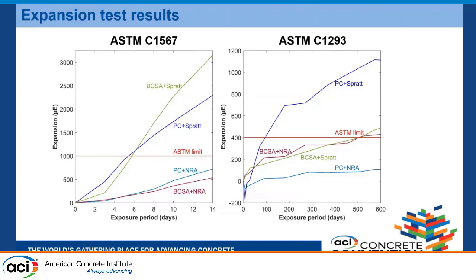If we compare with the results of the long-term test ASTM C1293, which again has a limit, the limit here is 400 microstrain. The performance is contradictory. Portland cement with Spratt shows the highest expansion, and the performance of BCSA with Spratt is significantly lower, with less expansion. Even though it still fails the test, as at 500 days it does cross the limit, the expansion is less than what we see in Portland cement with reactive aggregates. So that's again a good sign.